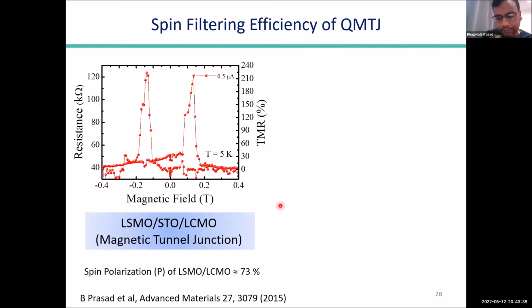We use LSMO or LCMO as electrodes. These two are called half metals. Typically, when people check their spin polarization, they show a spin polarization of 90%, but that is in ideal clean systems. The spin polarization matters here, especially when you are talking about tunnel junctions. We especially want to make sure of the spin polarization of these layers at the interface, because interfacial density of states matters for tunnel devices.